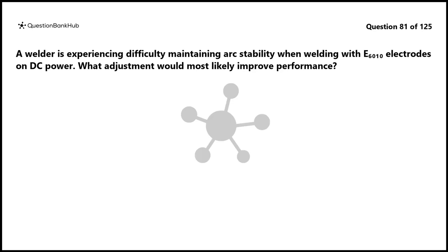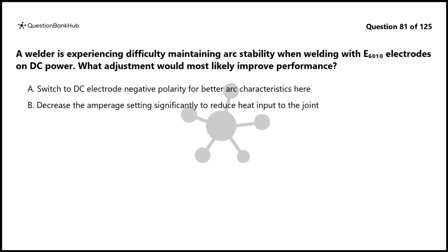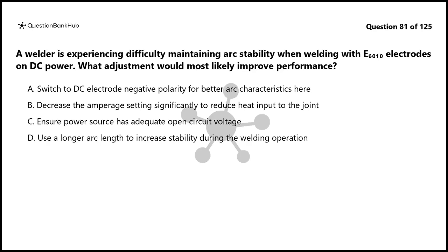Question 81. A welder is experiencing difficulty maintaining arc stability when welding with E6010 electrodes on DC power. What adjustment would most likely improve performance? A. Switch to DC electrode negative polarity for better arc characteristics. B. Decrease the amperage setting significantly to reduce heat input to the joint. C. Ensure power source has adequate open circuit voltage. D. Use a longer arc length to increase stability during the welding operation.